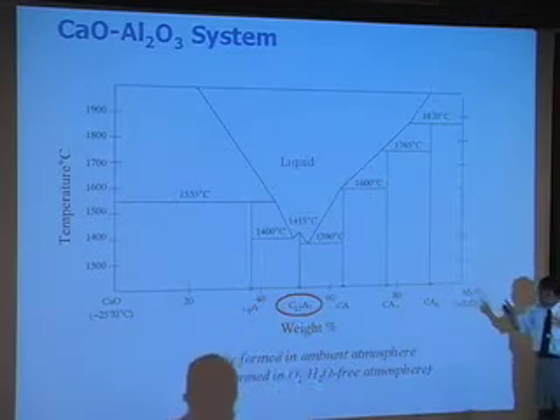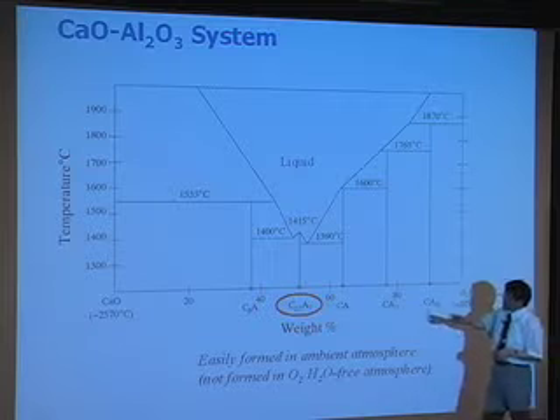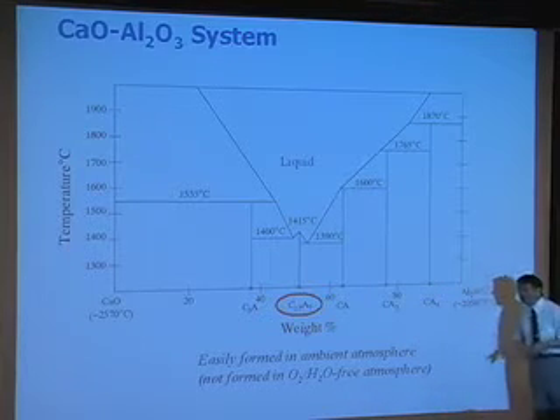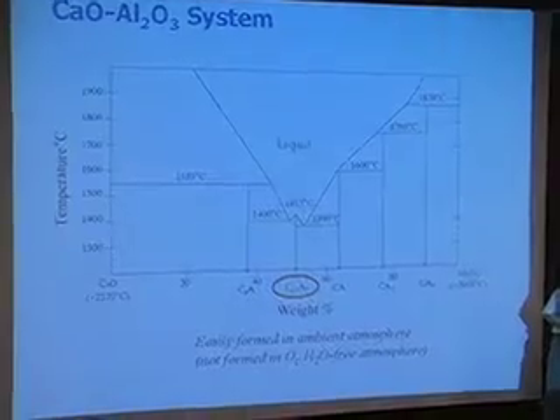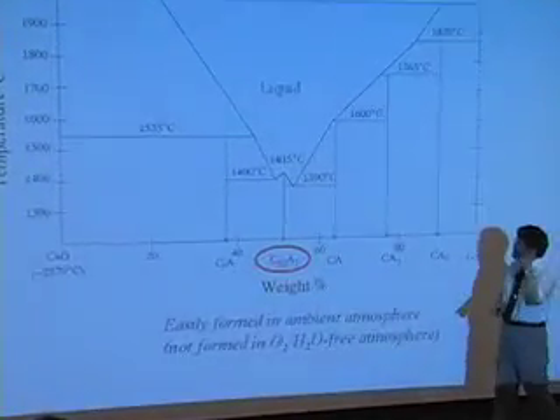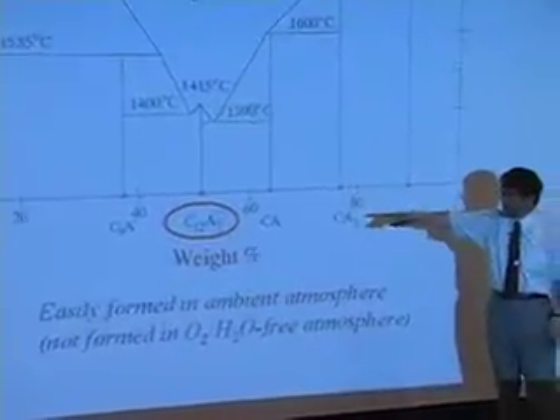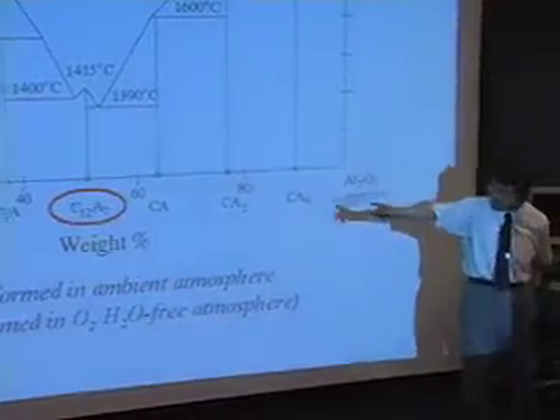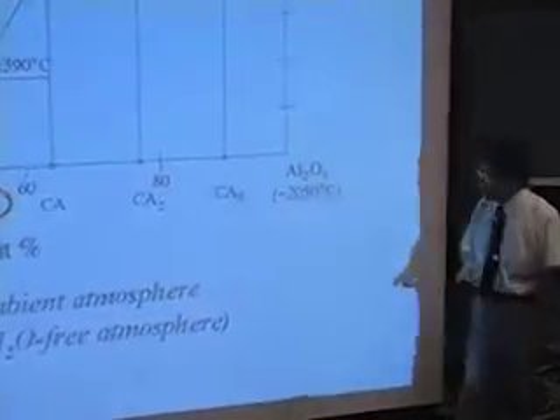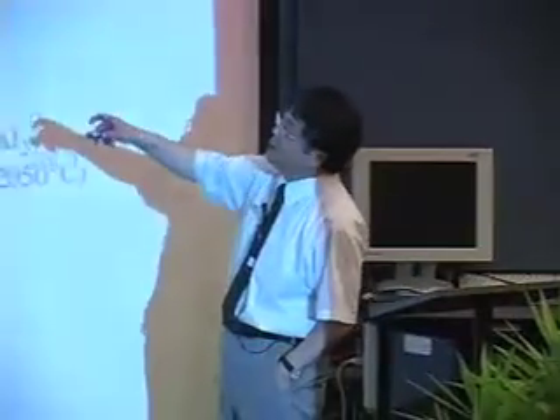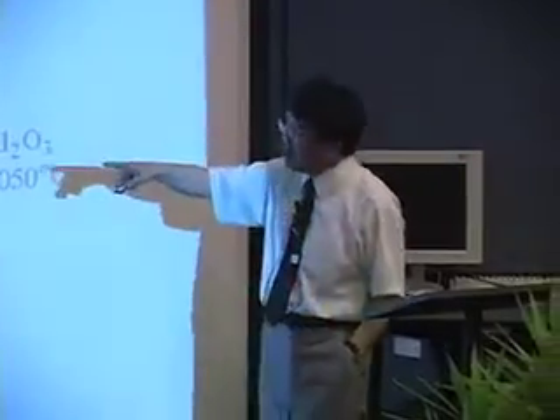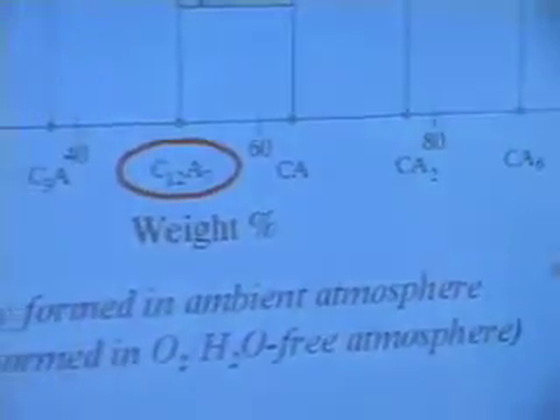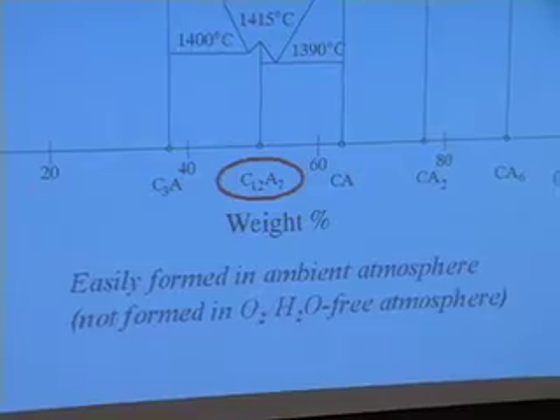The synthesis is very easy: a mixture of calcium carbonate and aluminum oxide, heated in air to 1000 degrees C, and you can obtain this material very easily. This material is a commercially used component of aluminum cement, so it's very easy to make. Most ceramic people know this material, but nobody believes it can be converted into a semiconductor.